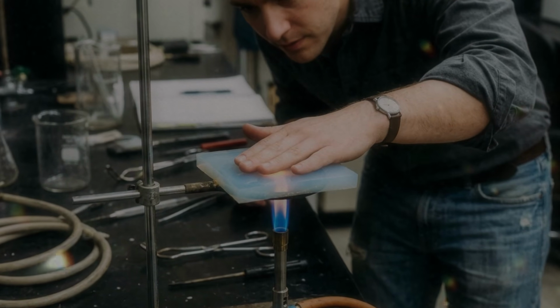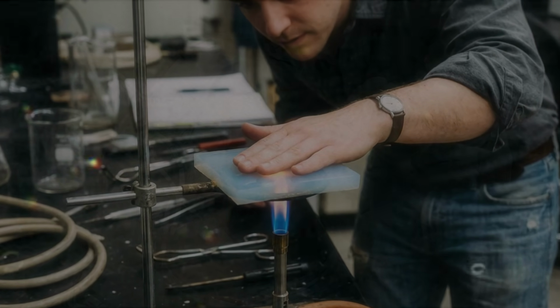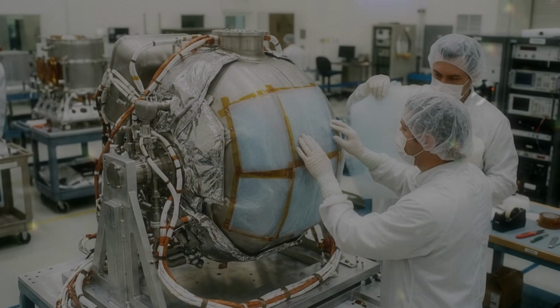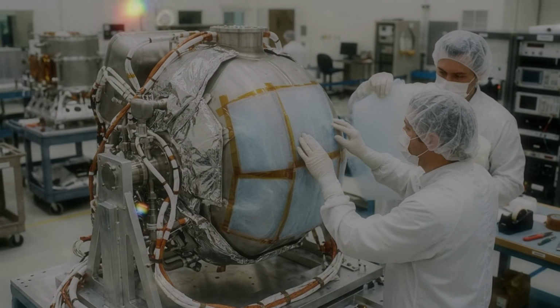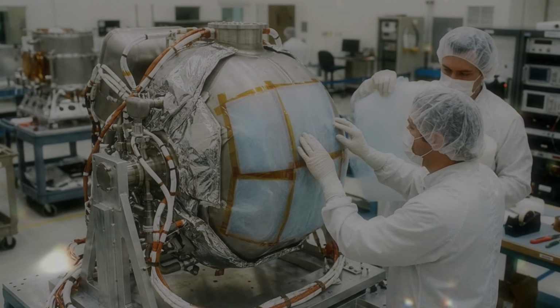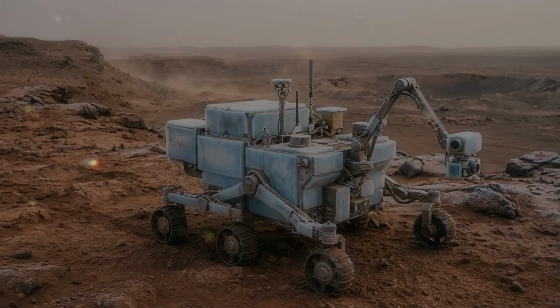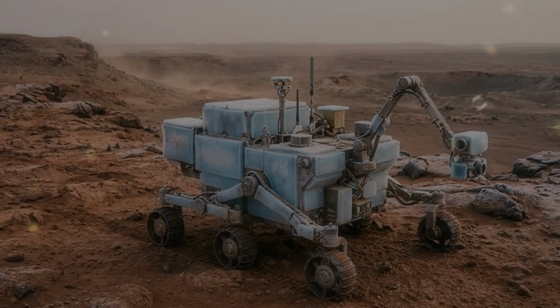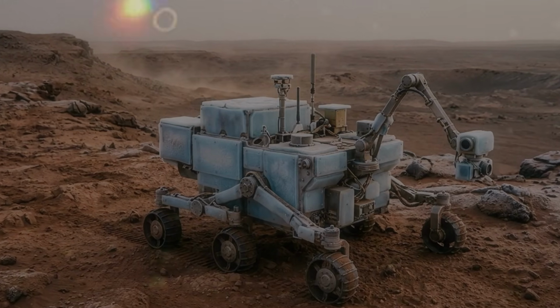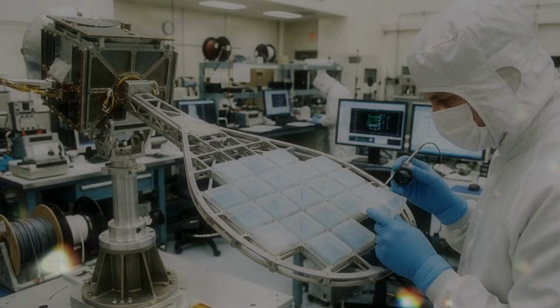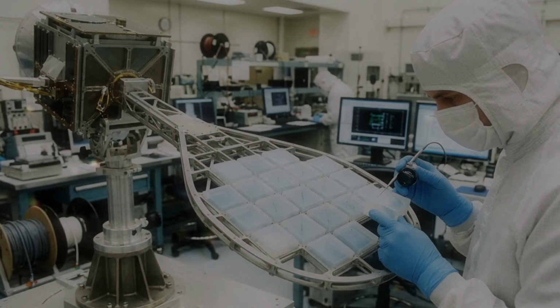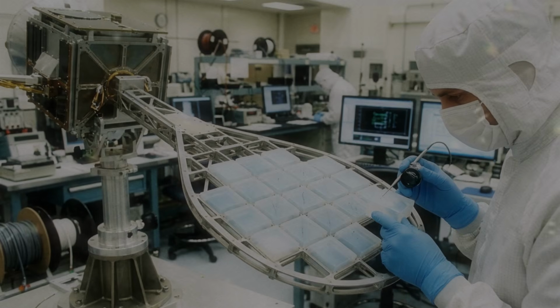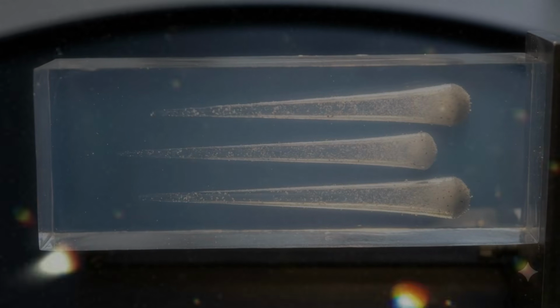The substance enters a supercritical state. It is no longer clearly liquid and no longer clearly gas. Most importantly for aerogel production, there is no curved liquid surface inside the pores. Without that liquid surface, the destructive pull of surface tension can be avoided. The solvent can be brought into the supercritical state and then released as a gas. The network is left behind with far less shrinking than ordinary evaporation would cause.